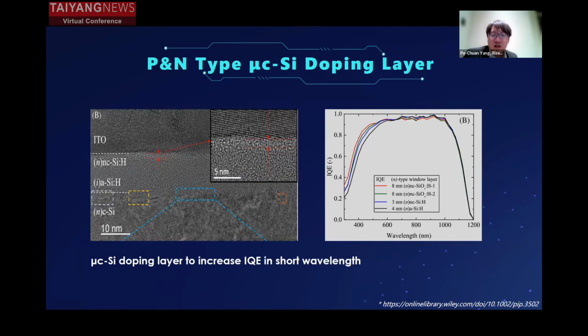And talking about microcrystalline silicon doping layer, it can improve ISC and the fill factor. For ISC, it is because the microcrystal silicon layer light absorption coefficient is much lower compared to amorphous silicon layer. And also we will introduce some oxygen or carbon to increase the band gap in the microcrystal silicon layer. Therefore, the short wavelength response is better. And for fill factor, that is because the microcrystal silicon has better conductivity. Therefore, it will decrease the series resistance in the cell, and in the end, we got a higher fill factor compared to using amorphous silicon layer.